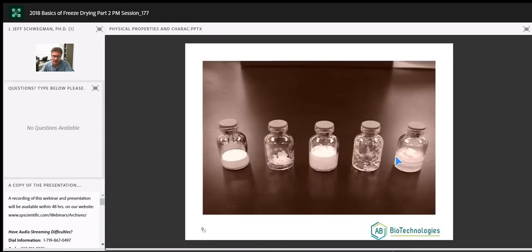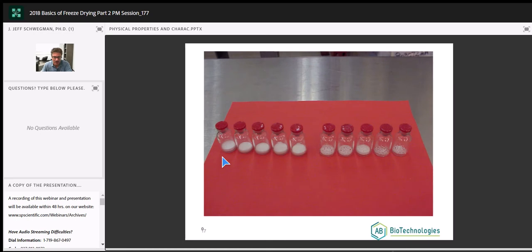Some of the other scenarios, this is called phase separation or ring formation. That is a classic example of problems with the freezing protocol. That completely, again, boiled. We dried it at too high temperature. All the material bubbled up the side of the vial as it boiled. This one's got some cracks. That's not necessarily a bad thing. Some excipients or active ingredients naturally will crack and pull away from the side of the vial. This one's in complete collapse, and that one looks pretty good.